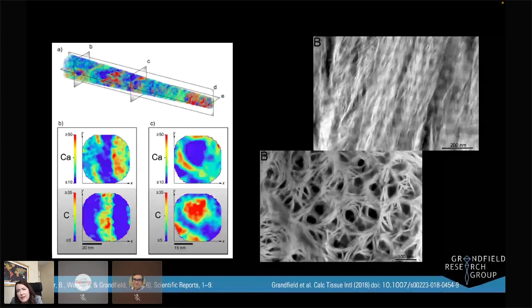This aligns quite well with what we see in transmission electron microscopy when looking at bone. In one orientation, we see nice collagen banding in our bone structure, similar to what we see in B, and in another orientation, we see this curved morphology of hydroxyapatite plates around collagen fibrils, quite similar to what our atom probe data shows us.